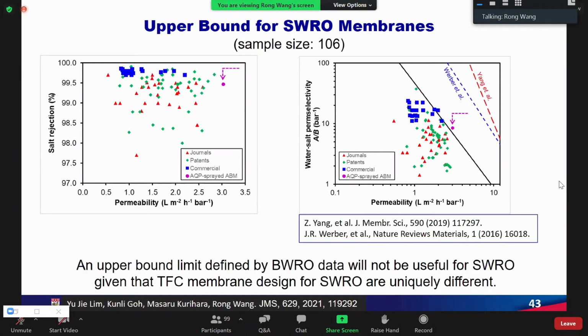Before I wrap up my presentation, I'd like to point out that it is important that we have a common understanding of the difference between SWRO membranes and BWRO membranes. Because of the high salinity of seawater, SWRO membranes should have a very tight selective layer, because the high salinity imposes stringent requirements on the membrane structure. The SWRO membrane for seawater desalination needs to reject salts as much as possible, so the matrix of the polyamide layer should be tight enough. The thickness will also change, becoming thicker compared to BWRO membranes.